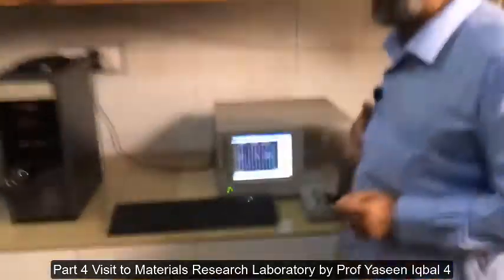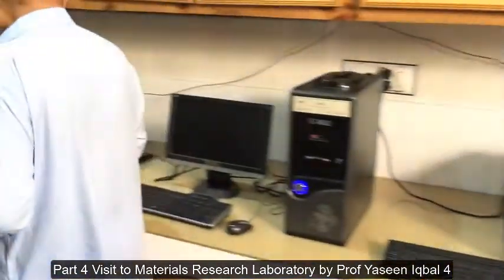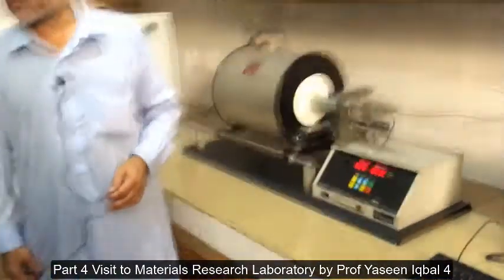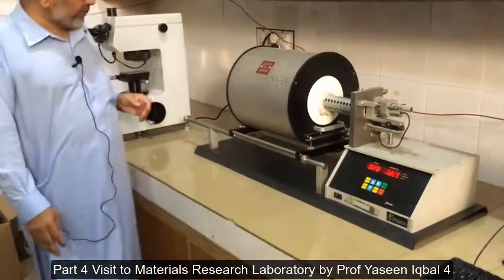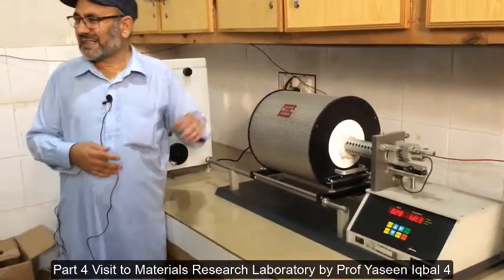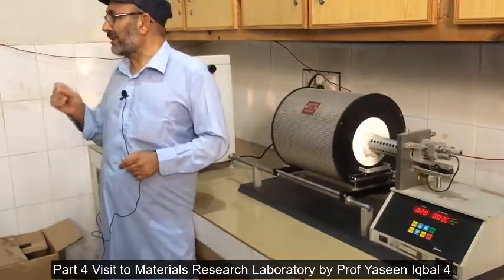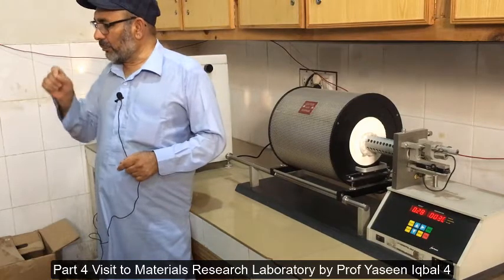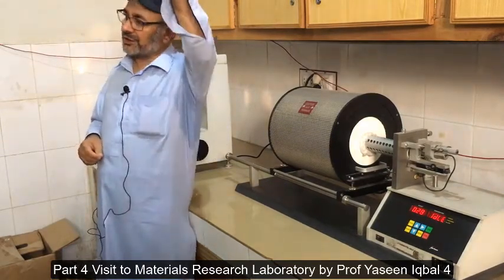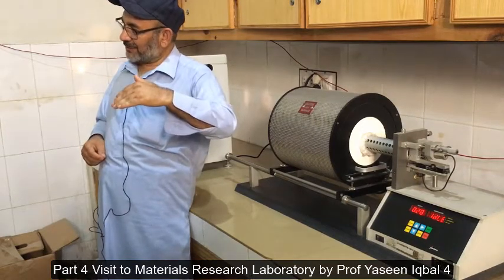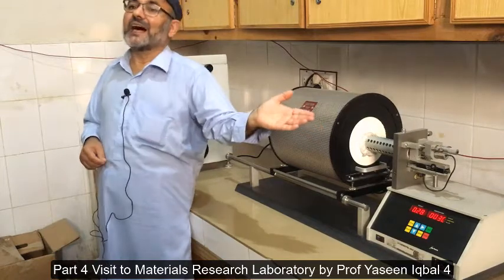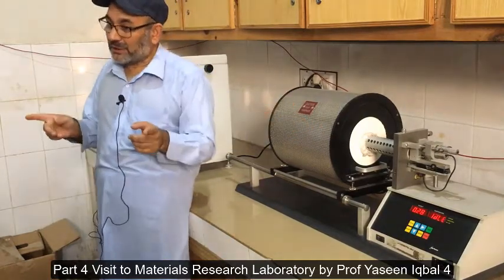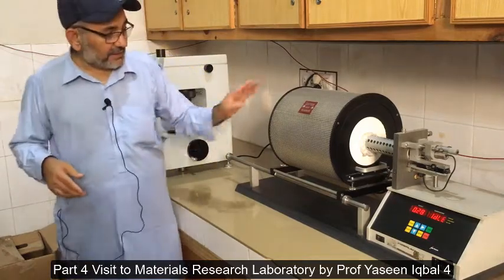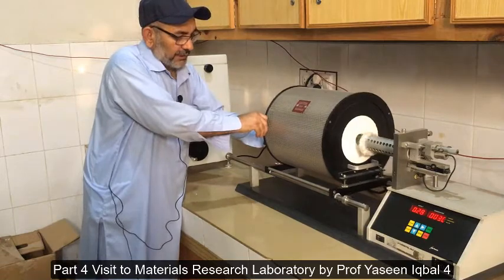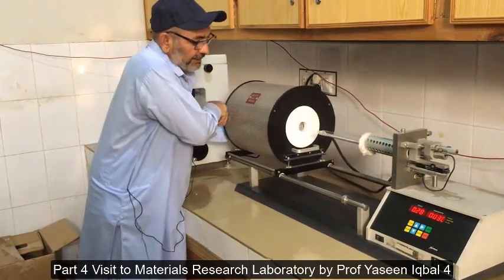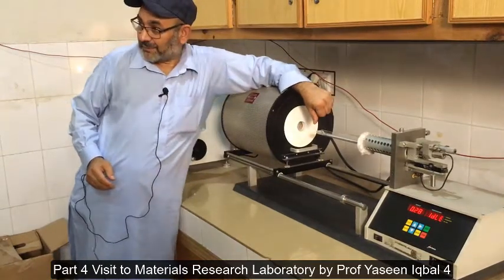This is a material analyzer, and it does the same job as I told you for the dielectric constant and those properties of the material. This machine is very interesting. It is called a glass dilatometer. What the glass dilatometer does, it does three things. It tells you about the glass transition temperature of the material. You melt the material, then you suddenly cool it to the glass transition temperature and slightly below it, and then anneal it in the next furnace. So when you don't know the glass transition temperature, you can't do that. And this machine tells you about the glass transition temperature of the material. The sample is placed here, right?